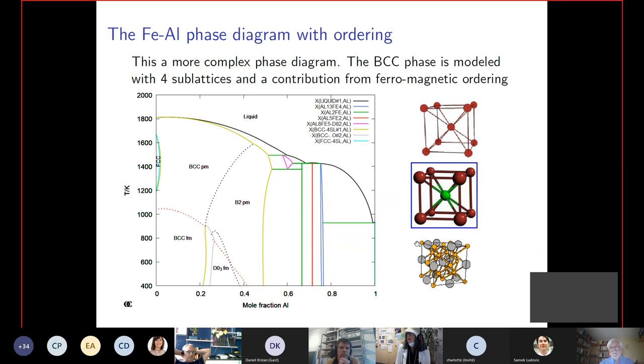And at low temperature, you can have a DO3 structure, which is even more complicated. Well, it's still basically a BCC lattice, but the atoms prefer different positions in the BCC lattice. So when you do modeling of the different phases, you have also some intermetallic phases with other structures, but the complicated phase to model here is all these regions in the BCC phase, including the magnetic transition.